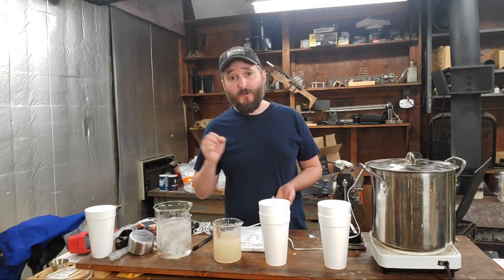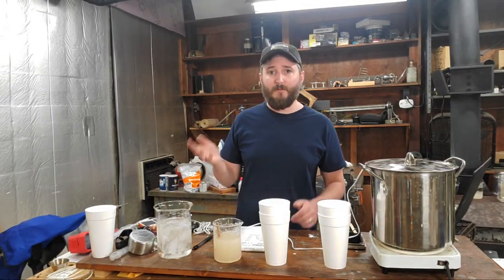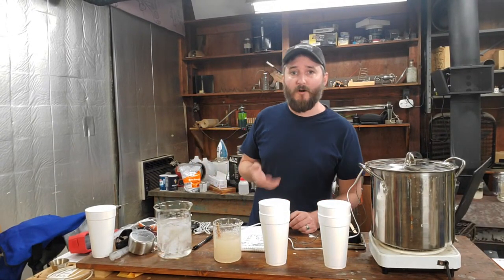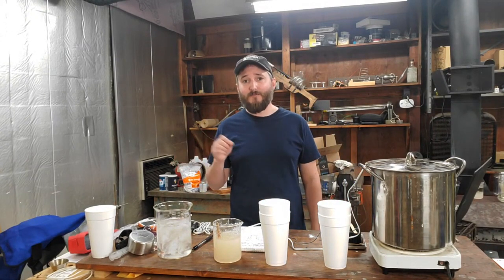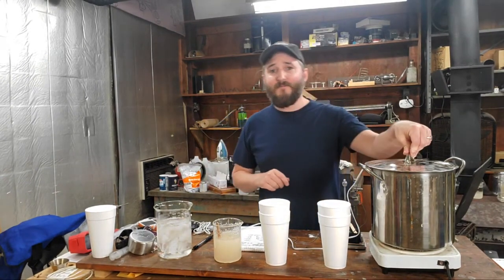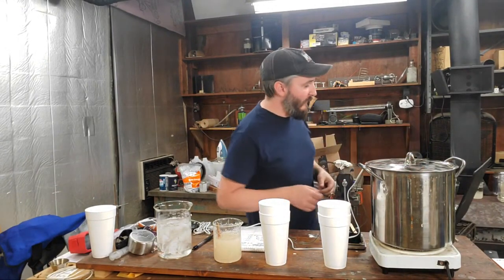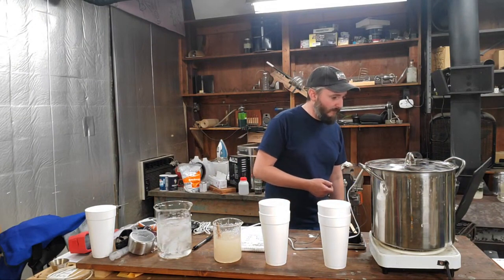However, if you get pure acrylic without any additives, which you can get as acrylic beads or powder online, it is transparent to almost all infrared light. And then you use the same method that I do for my infrared cooling paint, where you add a little bit of water to dissolved acrylic, and when it solidifies, you get a snow scattering effect. So that's another way that you could reflect most visible light and pass infrared.